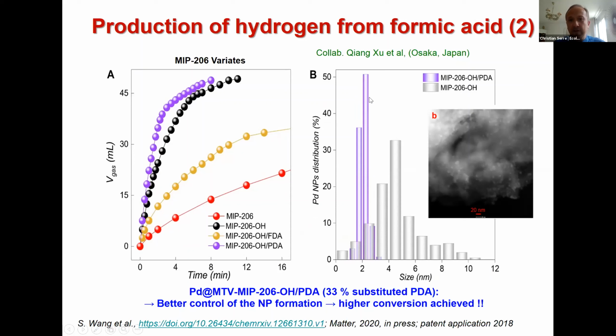But if we use a material that has 33% of substituted pyrazole dicarboxylic acid, you see that this time the particle size is around 1.5 to 2 nanometer, which is slightly lower than the pore size of the MOF, which means that probably the palladium nanoparticles are inside the MOF pores and are anchored to the pyrazole groups. And as a consequence, the catalytic activity, reduction of formic acid, is the highest with the pyrazole substituted. On the contrary, if you take the furan, the activity is lower than the pure MOF material.